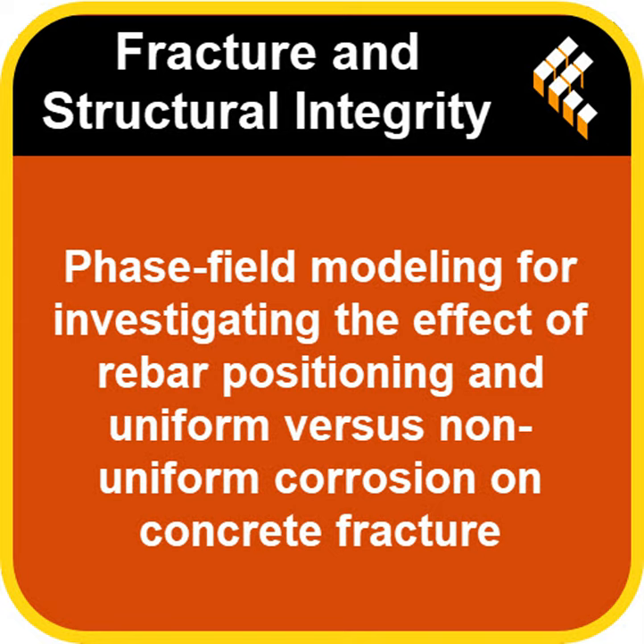For both corner and edge arrangements, and for both corrosion types, generally thicker cover was better, meaning it took significantly more rust expansion, higher values at both T1 and T2 before the cracks initiated and reached the surface. So more cover gives more protection, delays the damage. That makes intuitive sense. More concrete to push through.